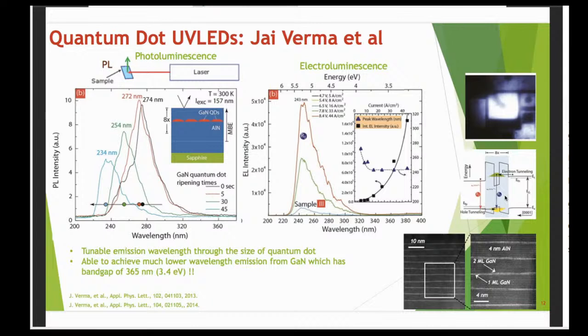And depending on the thickness of the quantum dot over here, we could tune the wavelength of emission coming out from this LED structure. The left graph that I'm showing over here is a photoluminescence spectra of the structure.